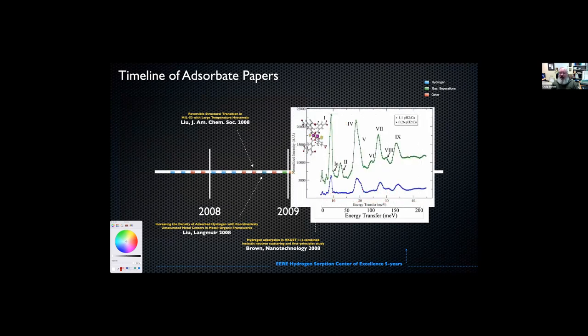We can also look at the hydrogen in those systems, and it took us a while to make a system that could generate parahydrogen instead of normal hydrogen, because the ortho and parahydrogen are fixed at a 25 to 75% ratio at room temperature, at all temperatures, if they don't have a catalyst to interconvert. So we use a catalyst to generate parahydrogen, which is in the rotational ground state, the J equals zero state, add it to the metal organic framework, and that allows us to probe J equals zero to all the sublevels above that.